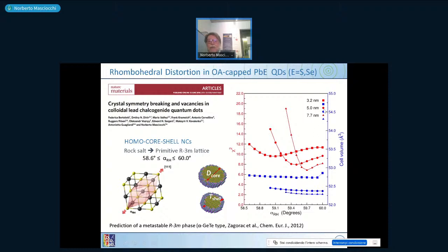When you go down with the size, then the angle becomes smaller and smaller. That means that if you shrink the material, the deformation is higher. If you go to particles which are bigger than 10 nanometers, you probably reach a level where the cubic phase is stabilized. So that means that only at very low crystal size, stabilization of this distortion is possible.